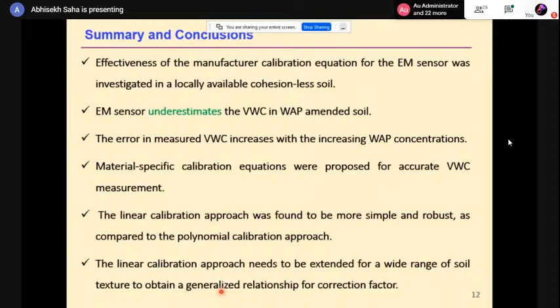So we have used two material specific calibration equations, and we found that the linear calibration approach is more simple, and it can be extended for a wide range of soil textures to obtain a generalized relationship to calculate the correction factor, which needs to be multiplied with the sensor data to get the actual water content in the field.